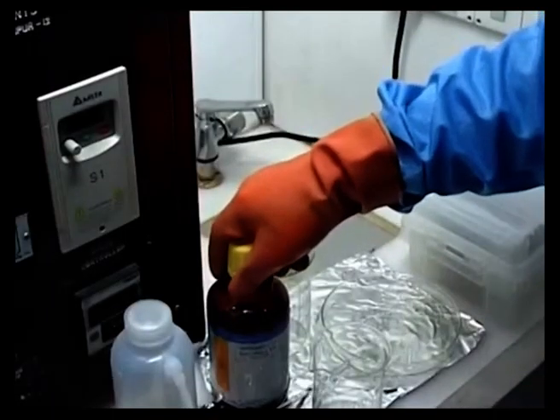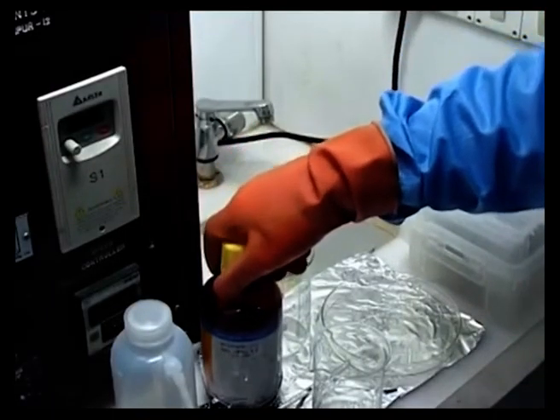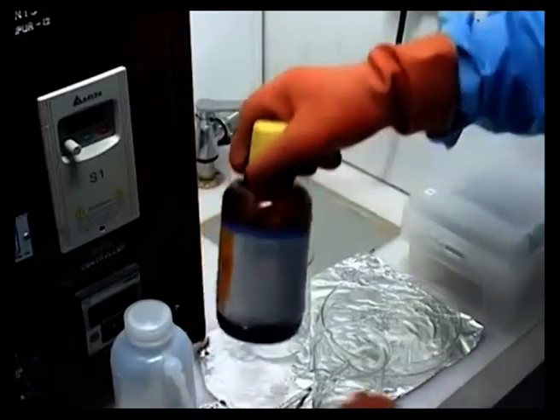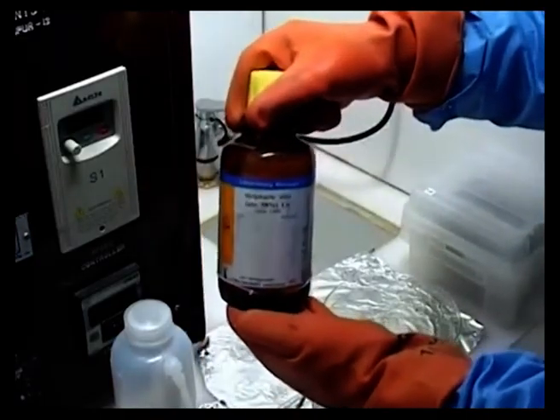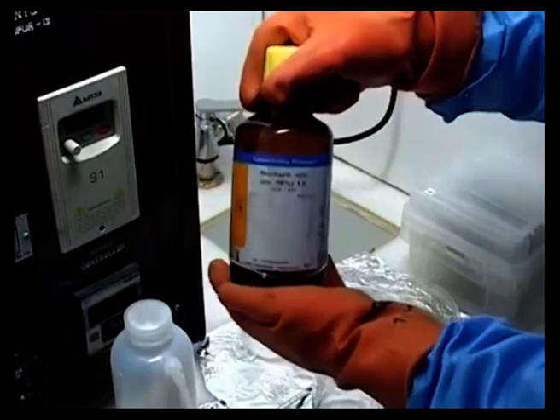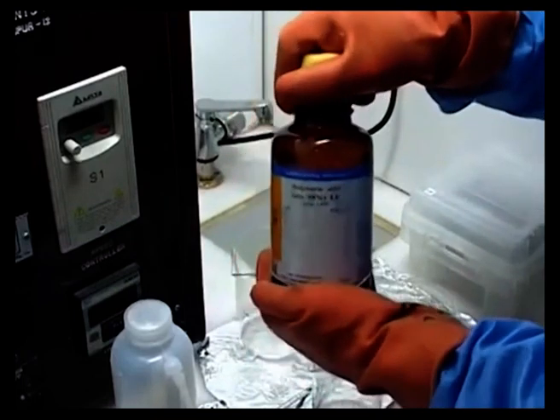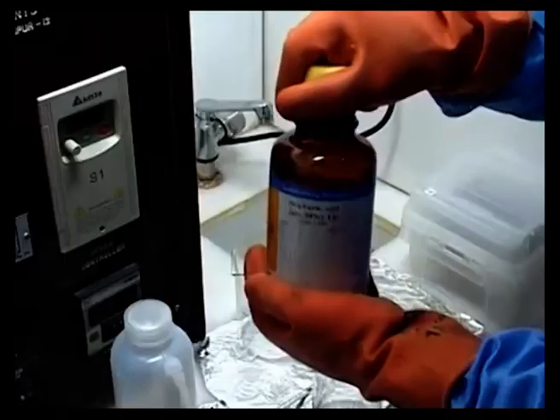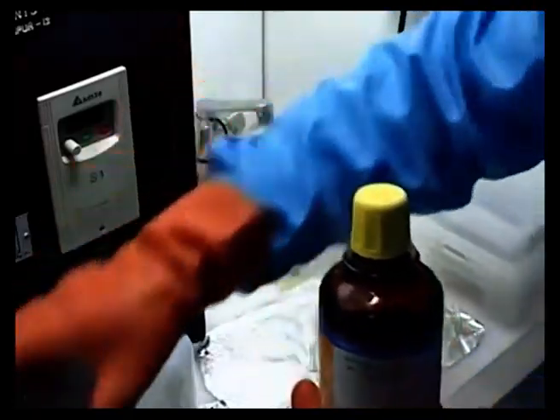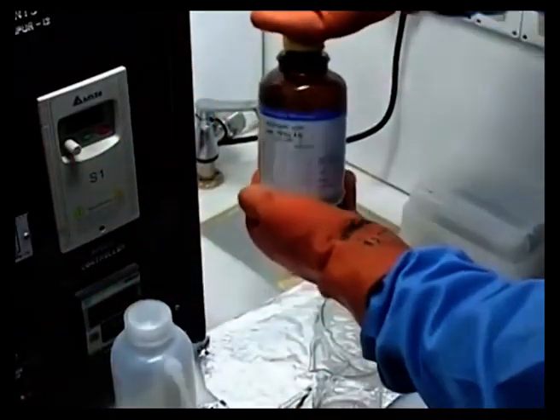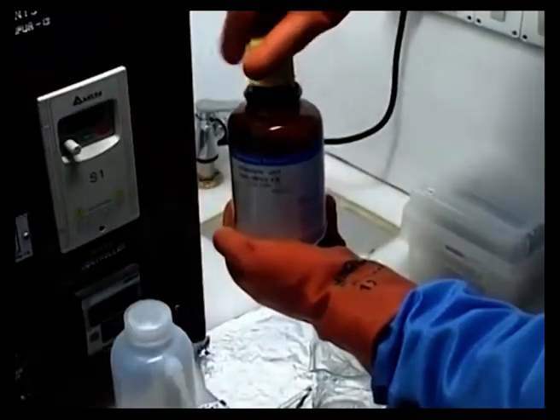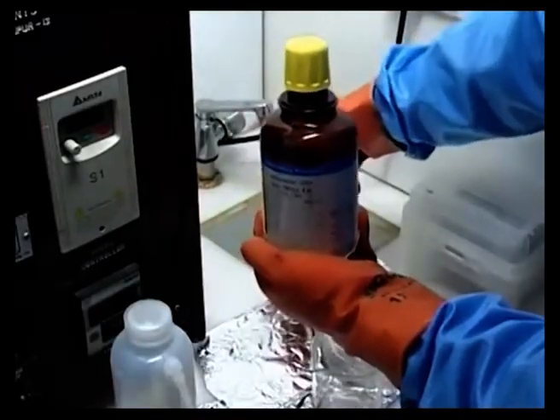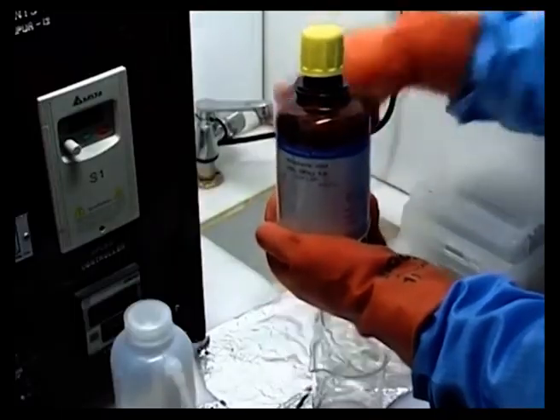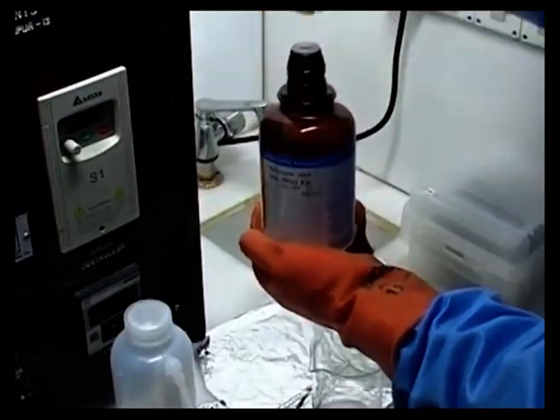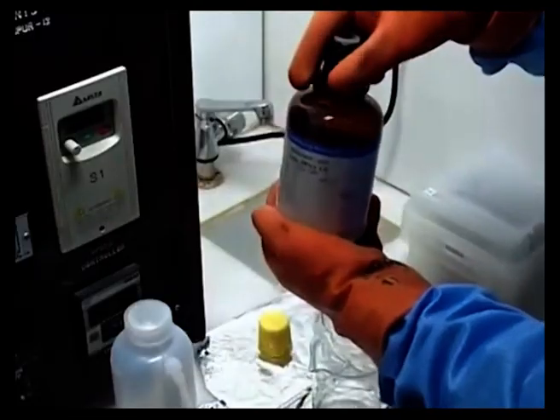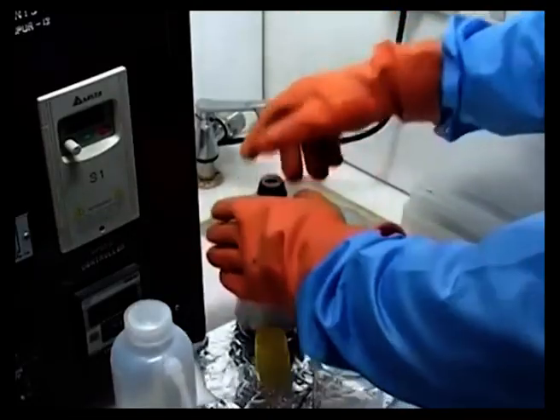So what we do is basically pour about, in this case about 90 ml of sulfuric acid, 98%. As you can see, this is a very, very dangerous chemical, and it has to be very carefully used. And then we'll mix about 30 ml of hydrogen peroxide. So what we do here is the following. We do all this pouring over this drain, so that in case there is a spillover, everything goes down the drain. Okay, so essentially opening this sulfuric acid bottle is also to be done very carefully.